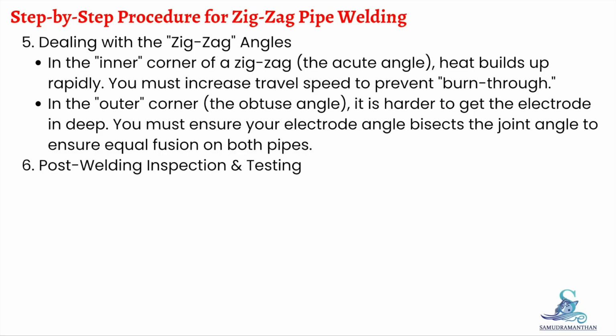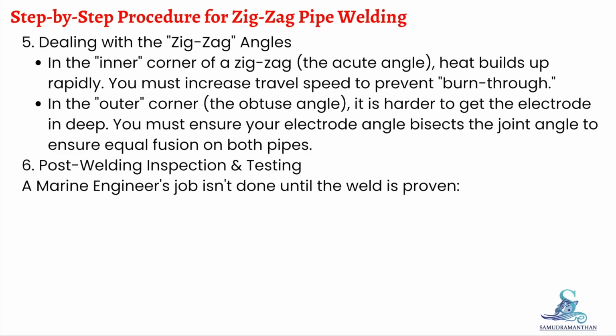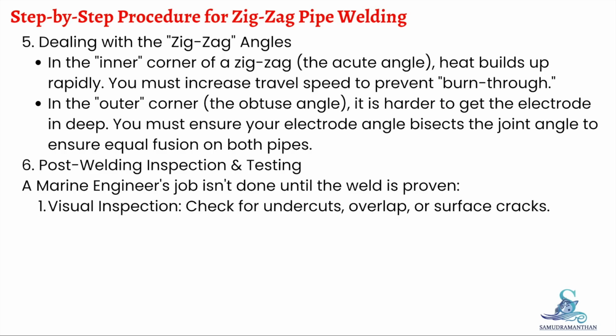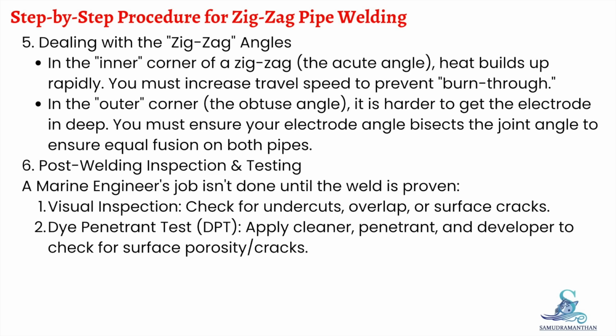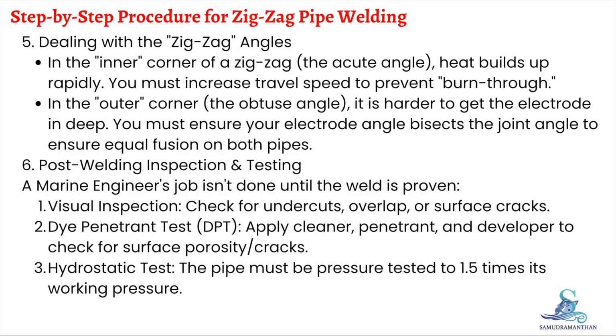Post-welding inspection and testing. A marine engineer's job isn't done until the weld is proven. Visual inspection: check for undercuts, overlap, or surface cracks. Dye penetrant test, DPT: apply cleaner, penetrant, and developer to check for surface porosity or cracks. Hydrostatic test: the pipe must be pressure tested to 1.5 times its working pressure.